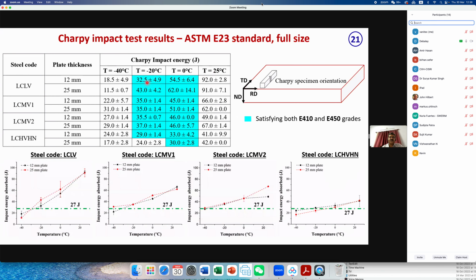Charpy impact energy, all these blue colored regions are showing where we are meeting the properties. We are targeting 27 Joule down to -20. So 0 degree also there is requirement of 27 Joule, -20 also. So in all the new grades we are meeting satisfactorily the 27 Joule toughness. Only in 25 plate, -20°C, we are falling a little short,